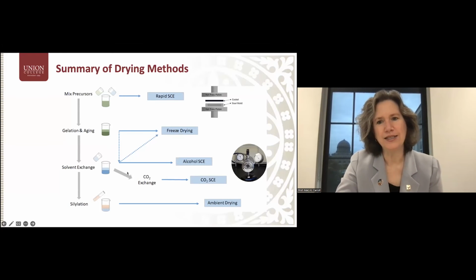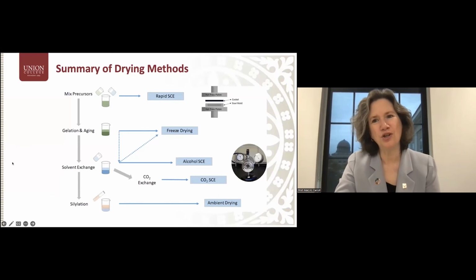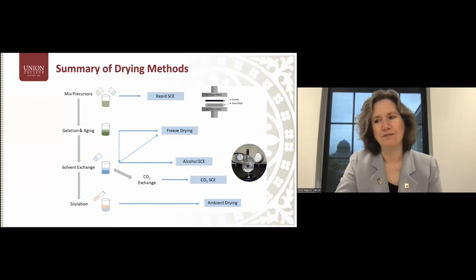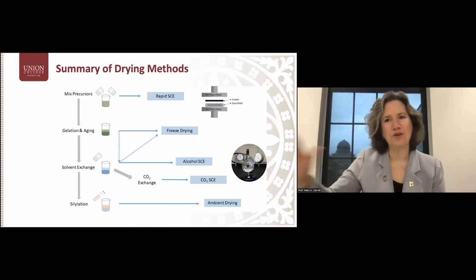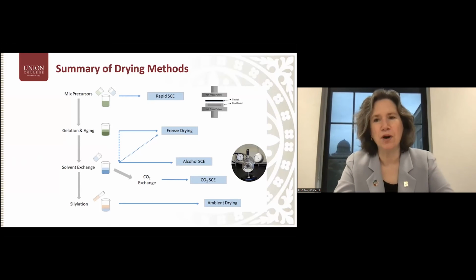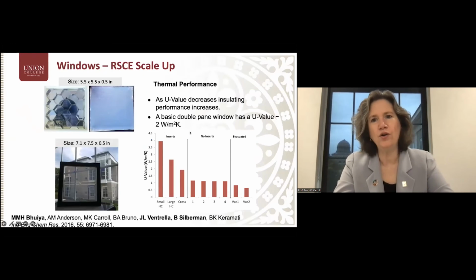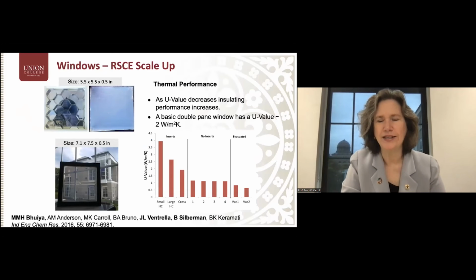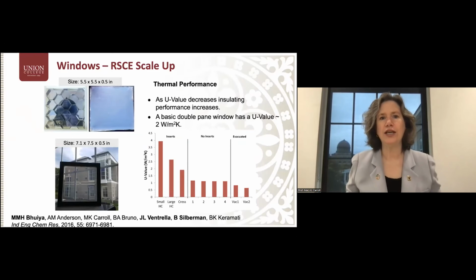The AeroShield process is based on a more traditional sort of autoclave-based system, where again, they're mixing it together, letting it gel, doing solvent exchanges, and then doing supercritical extraction in very large autoclaves using CO2 supercritical extraction. We are all making monolithic, highly transparent aerogels, and the question is, can we make them large enough in a method that is suitably aligned with manufacturing to allow this to enter the market. So what we're seeing with our own work, and I'm going to talk now about work we have done at Union and in conjunction with our startup company, Sun-Through LLC, which has been incubated at Union, is looking at scaling up of the process.